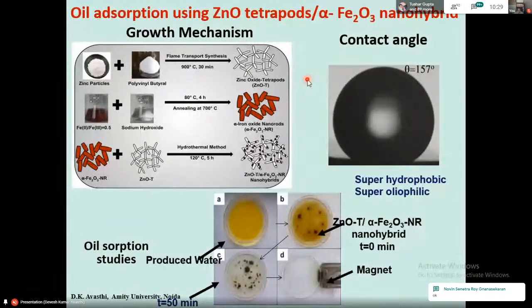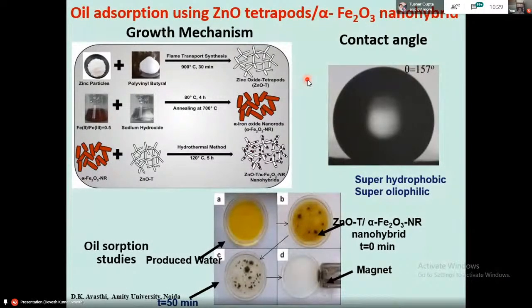So now one more effluent, from the oil industry: there is a lot of oil contamination in water from this kind of industries. So here we did some work using zinc oxide tetrapods, which are the same thing I have shown earlier, and then we have an iron oxide nanohybrid. That means a nanocomposite of zinc oxide tetrapod and iron oxide. So in this slide, you can see that the zinc oxide tetrapods are made by flame transport method, and this is the shape of the zinc oxide tetrapods. And the SEM image you have seen earlier in the previous slide.